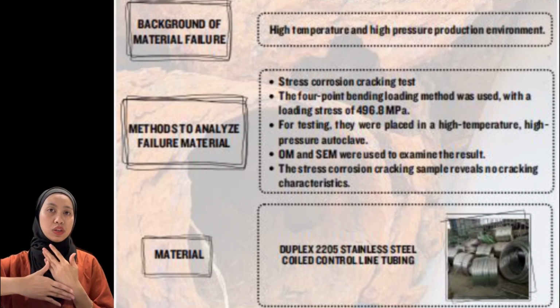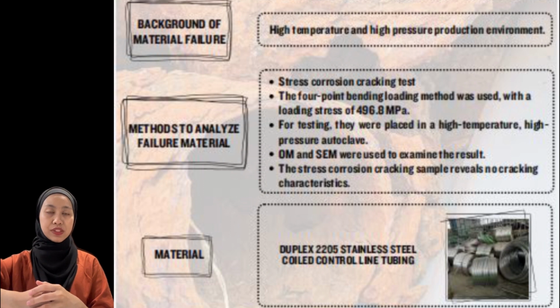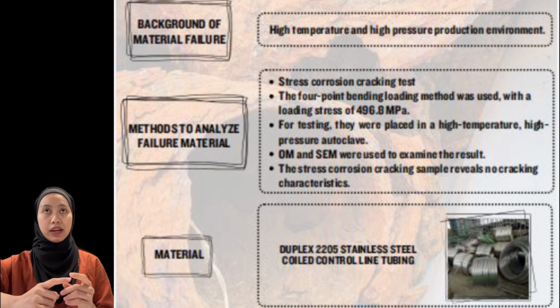Hi, my name is Aiman Sofia. So we go to the background of the material. Failure is related to the high temperature and high pressure. The method to analyze failure is the stress corrosion cracking test, or SCC test. In the production environment containing CO2, carbon dioxide, and hydrogen sulfide, the SCC sensitivity of 2205 duplex stainless steel needs to be further evaluated under high temperature and high pressure conditions.